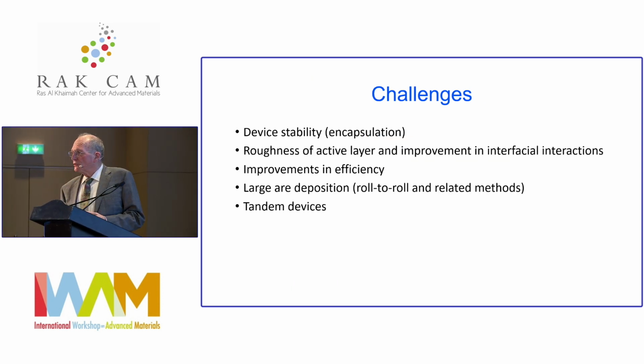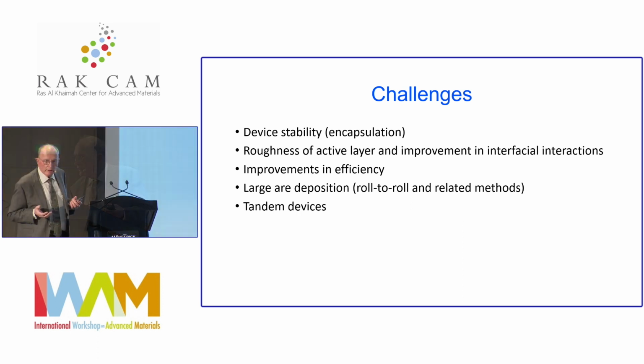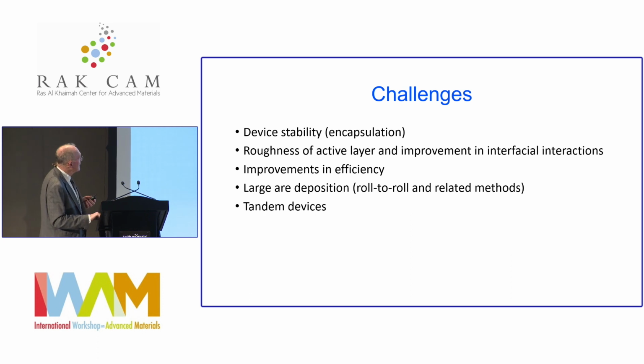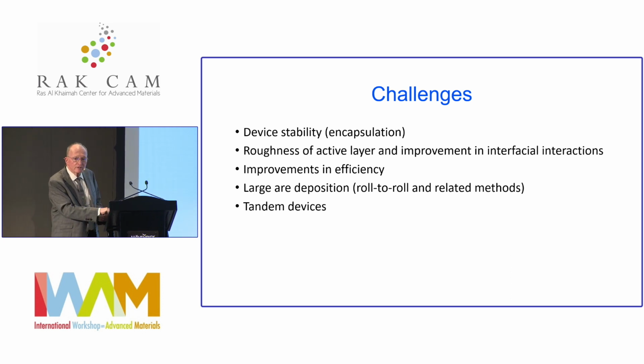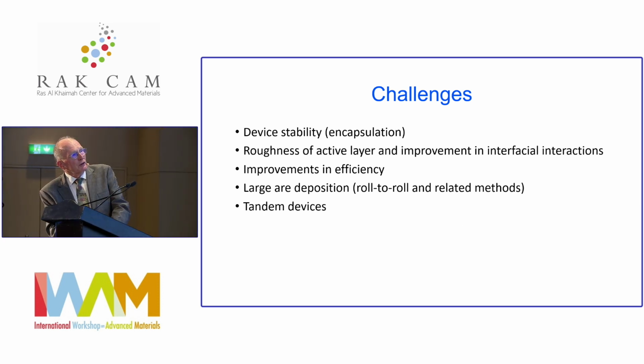So what are the challenges to get on? Because this is clearly something that everyone's got quite excited about. Stability. Perovskites aren't stable, neither are the organic materials without protection against photooxidation. So you need to encapsulate all these devices. And it turns out that one of the most expensive components is the encapsulation material in this work. So encapsulation, because perovskites certainly don't like water, and there are other reasons that help them break down.